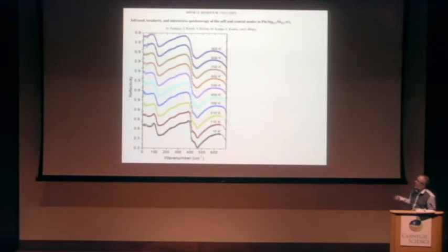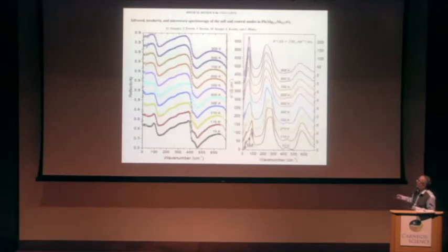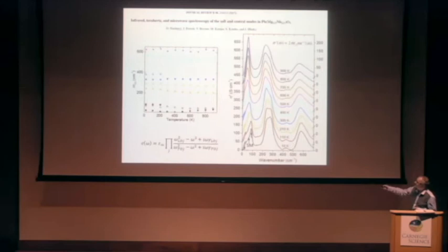we focused on high temperatures, or on all temperatures, that we have infrared reflectivity spectra from 10 Kelvin to 900 Kelvin. And it looks like there is no dramatic change. But when we evaluated the spectra, there is an optical conductivity calculated, which is related to dielectric losses, the peaks correspond to phonon frequencies, and the low frequency data, also from terahertz spectra, show clearly the splitting of the modes, and there is a temperature dependence of all phonon frequencies showing